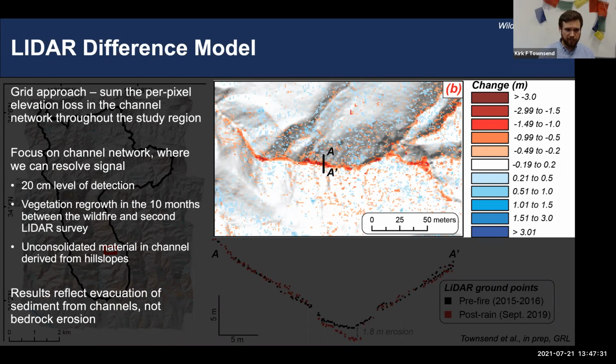And here I'm going to focus mostly on the channel network rather than the hill slopes for a couple really important reasons. The first being that just because of some inherent uncertainties in how both topographic data sets were acquired, we can really only resolve change that's more than 20 centimeters. And we know that change on the hill slopes is generally less than that, whereas the change in the channel network usually exceeds that quite a bit.